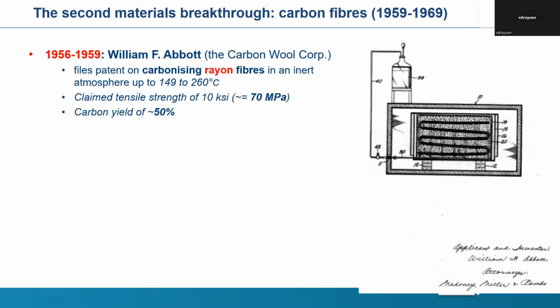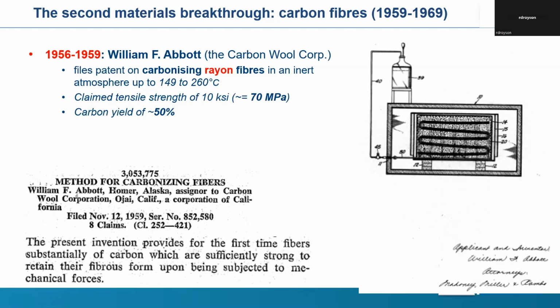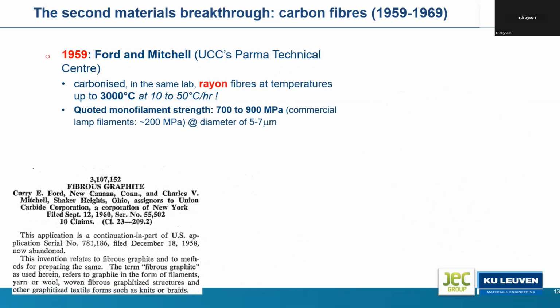So a similar attempt to make carbon fibers, but now not carbon nanofibers of Bacon, but real fibers which you can handle, was done by William Abbott in the Carbon Wool Corporation, and he was carbonizing rayon fibers, but at very low temperatures, below 260 degrees, and as a consequence, the mechanical properties were very low. They weren't really focusing on mechanical properties. The carbon yield was only 50%, whereas now we reach much higher values. So this is the development at Carbon Wool Corporation.